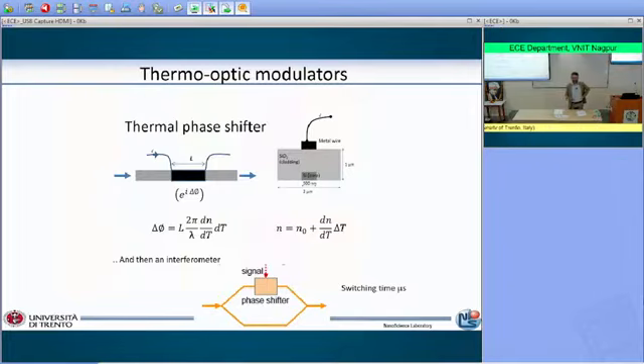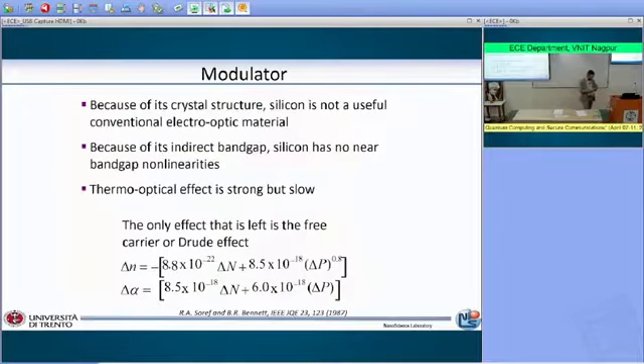So this is very effective. It costs nothing because it's a piece of metal on top of the silicon, but there is a problem. The switching time is long, a few microseconds. Why so long? Because you have to heat up the silicon, and then you have the inertia. Once the temperature of the silicon has increased, this heat has to flow away in order to get back to the initial condition. Therefore, the typical frequency at which you can encode your signal into this Mach-Zehnder is on the order of megahertz, which is low for optical transmission.